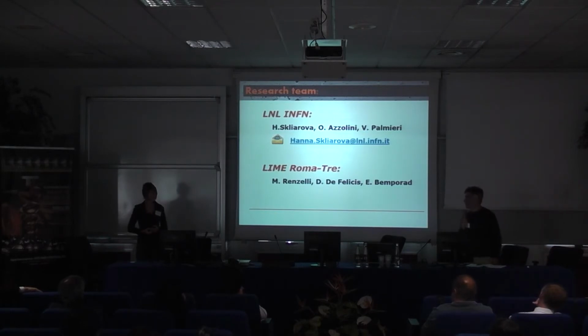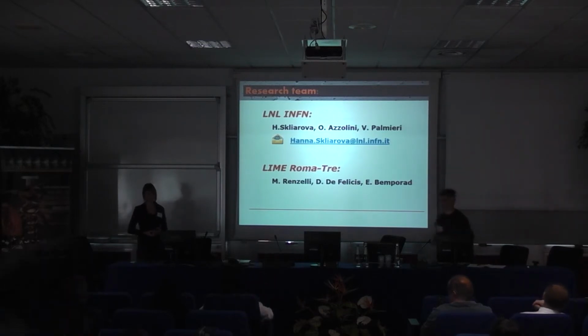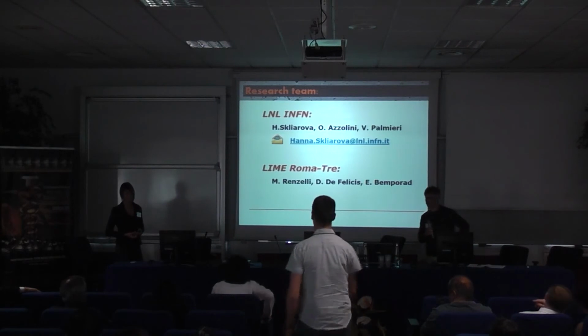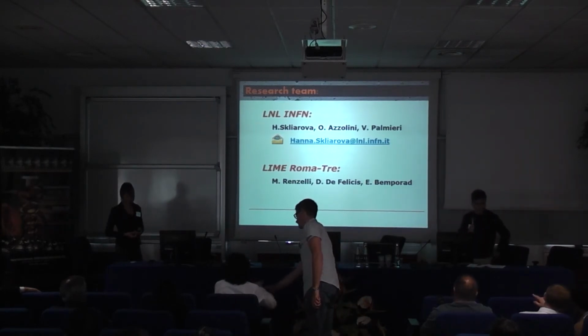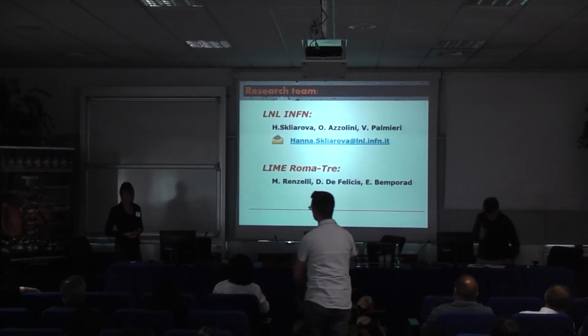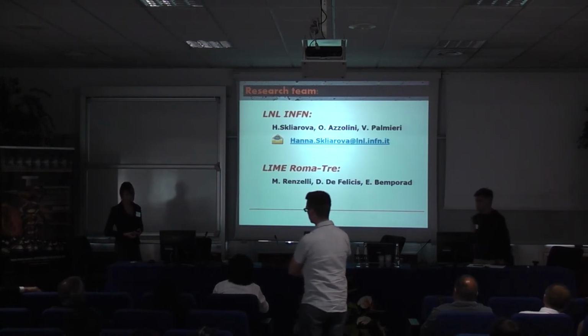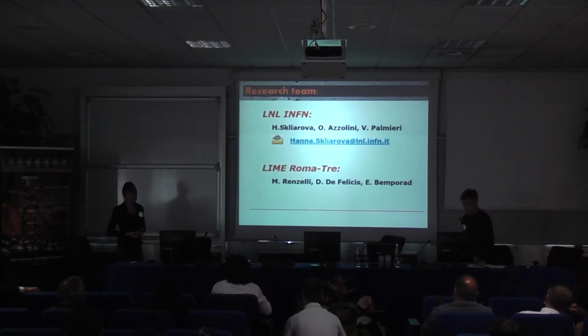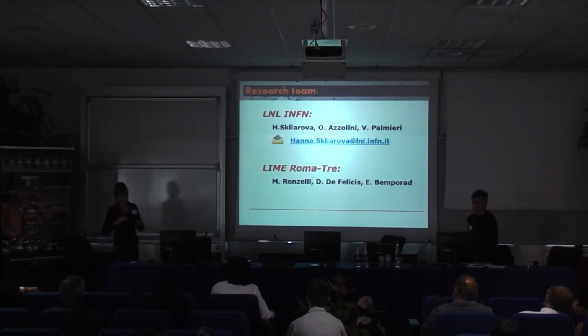Okay, questions for Anna? We have quite some time. So, do you have an idea to apply your porosity test to our niobium copper sample? You should use another acid, right? Okay, there is one idea. You can use copper sample, deposit first aluminum, and after deposit your niobium in a technique that you are going to check. And you can use the same test.